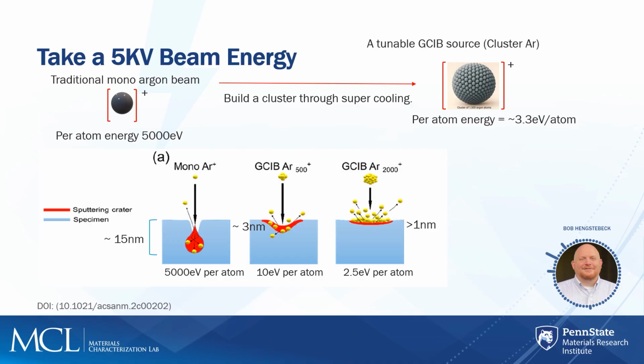The new GCIB source is going to use adiabatic cooling. Essentially, they're going to take a high pressure of argon and pass it through a very small aperture into a low vacuum side, speeding up that argon to supersonic speeds. And in that process, you get supercooling, and that allows you to create these clusters. Depending on the original pressure, the cluster size, and what the vacuum was before or after the aperture, you can basically tune to different cluster sizes. You can have as small as 50 atoms, or you can go all the way up to 10,000 atoms. We're not going to be working in the 10,000 atom range, but you have this ability to control the cluster size.